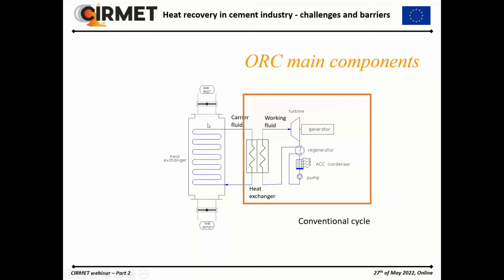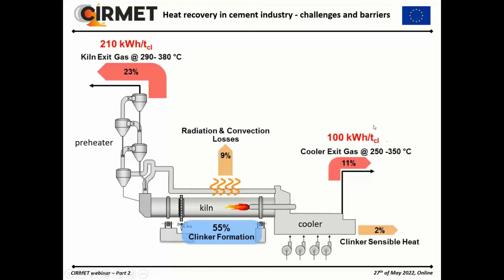From the heat exchanger, the gases heat a carrier fluid. This fluid transfers the heat to a working fluid that expands in a turbine, and then is cooled and condensed in a condenser, and with the pump, the working fluid circulates. At the same shaft of the turbine, we connect a generator, so we get electricity. That's a conventional cycle. In the direct cycle, we erase one of the exchangers, so we increase the efficiency of the system. In a burning system, we obtain more or less 210 kilowatt-hour per ton of clinker from the preheater and 100 kilowatt-hour per ton of clinker from the cooler.